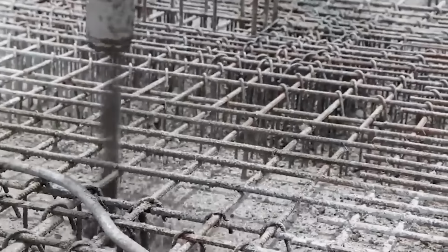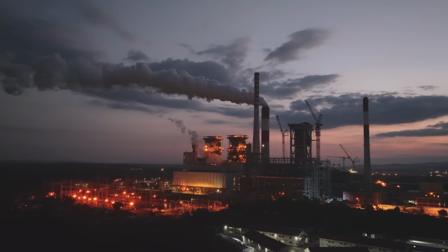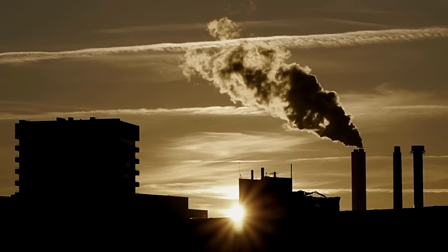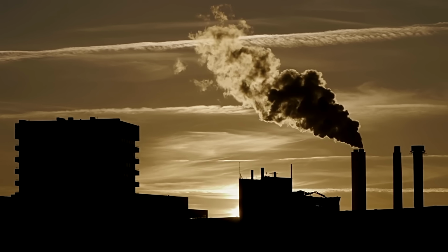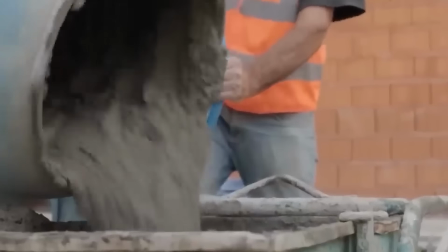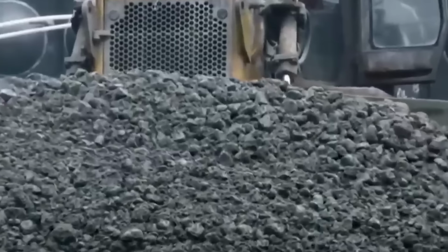None of this requires a kiln. None of it requires limestone decomposition, which means none of it produces the direct chemical carbon dioxide release that makes ordinary cement production so difficult to clean up. The material isn't fired into existence. It is chemically grown at ambient temperature out of two things the coal and steel industries already produce as unavoidable byproducts. Documented studies on fly ash and slag-based geopolymer systems have measured compressive strengths well above typical structural concrete benchmarks, with some formulations exceeding 65 megapascals and select mixes documented above 80 megapascals, comfortably in the range required for demanding infrastructure applications, not just experimental samples.